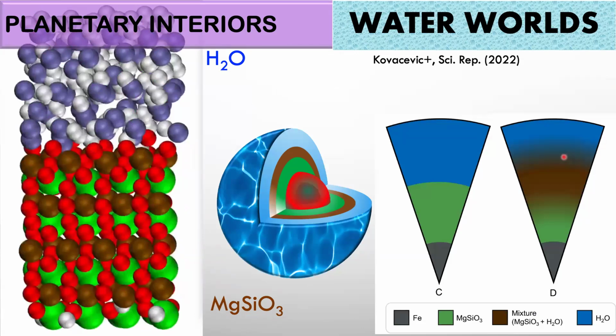So this has changed basically the picture that we have for the interior of these eventual water worlds, where rather than really nicely separated layers of water and silicates, we think that there's a gradient of composition, which makes the problem even more difficult to track because it will alter convection in these planets and the heat transport. But it's important to consider if you want to have a realistic picture of what's happening inside of these planets and how they cool down.